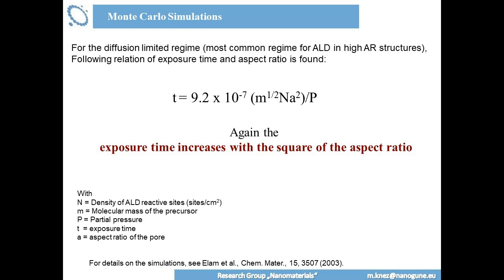And the aspect ratio of your pores or your structures is really a very, very important factor here, because you need to adapt your process and you need to give the precursors enough time to diffuse from the gas phase into your pores and into your structures.